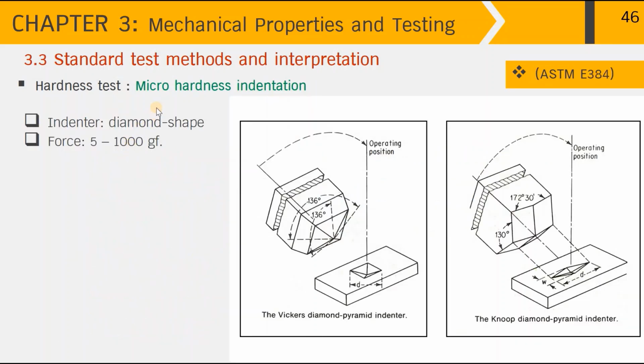And another type of Vickers hardness test, as I said before, we can apply a small level of load to obtain micro hardness indentation. And for this type, we can either use the Vickers diamond pyramid indenter or the Knoop diamond pyramid indenter. As you can see, the diamond pyramid comes with the square base, but the Knoop has the reduced dimension along here, so it's appropriate to measure the case hardening of the metal surface. So we have to select either the Vickers or the Knoop